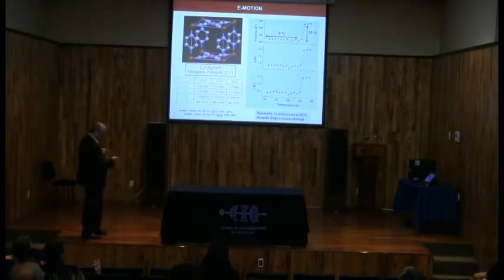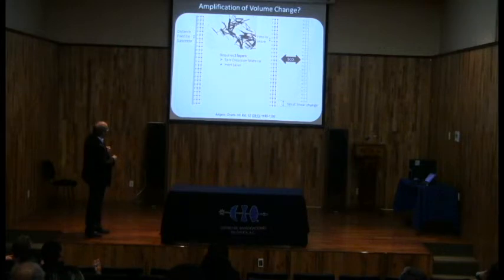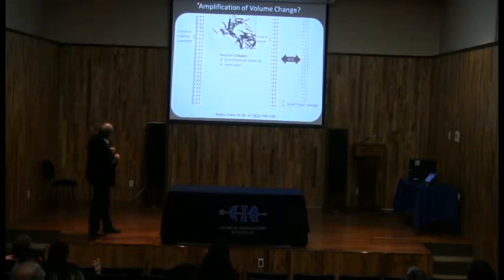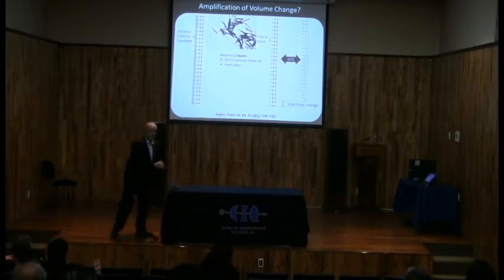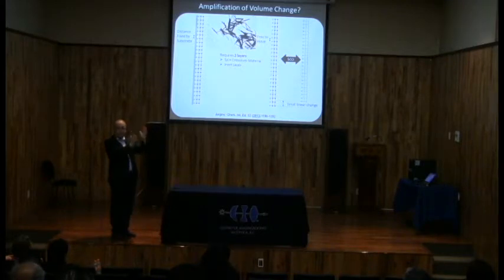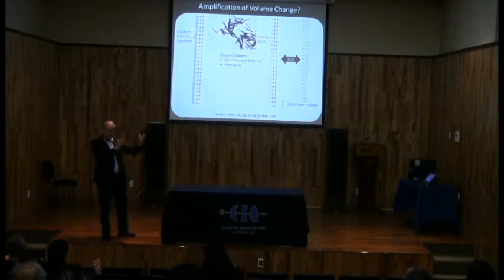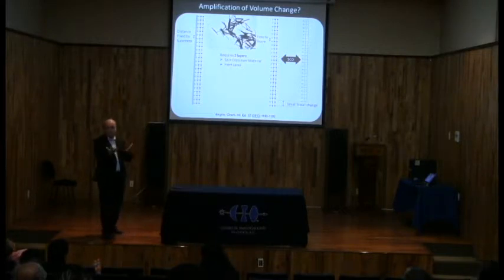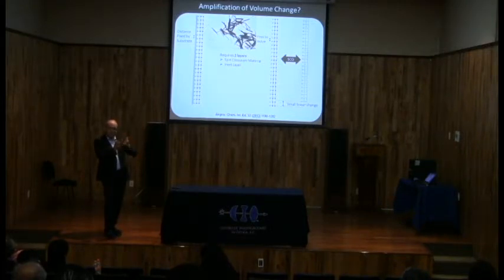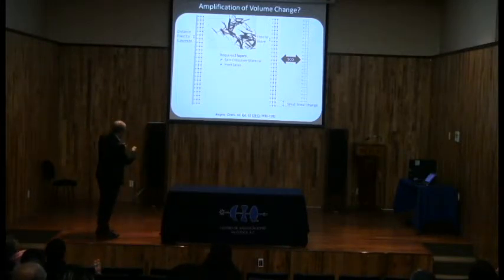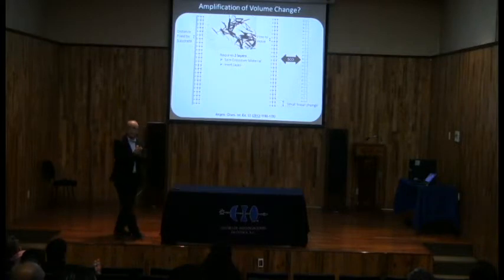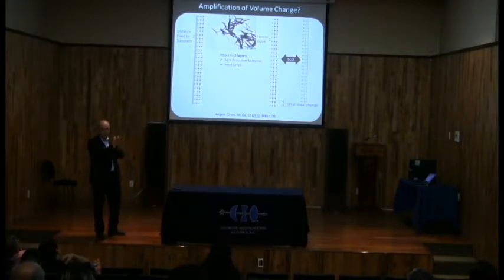Okay? And then what we said is that if we take our rods here, in principle, if we combine our rod with, for example, a gold surface here, to have a bilayer, you will have a bilayer like that. You have one part which wants to change its volume, and the other one, which is gold, which has the same dimension. That means that if you switch your system from low spin to high spin, you change volume on only one part of the layer. Okay, on only this part here, you have change of the local distances here. That means that as a function of the crossover temperature, you expect to have the actuation.